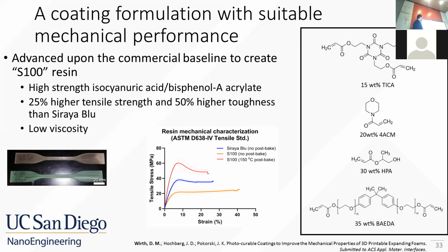It's an isocyanuric acid bisphenol A acrylate-based high toughness resin, boasting 25% higher tensile strength and 50% higher toughness than Siraya Blu. And most importantly, it has low viscosity, so it can be applied with an ordinary cordless paint sprayer.